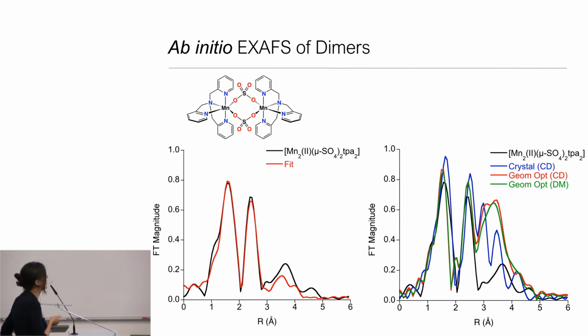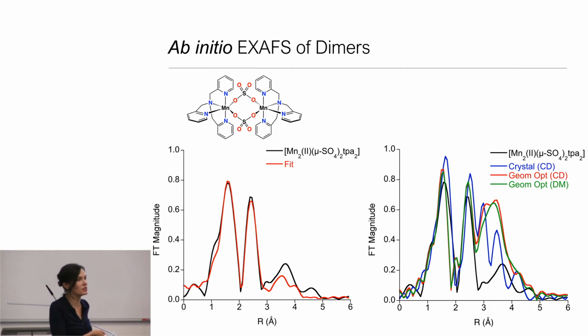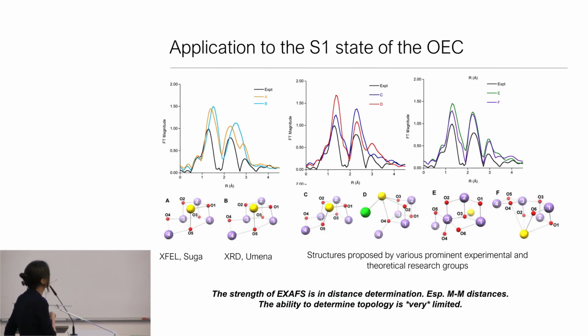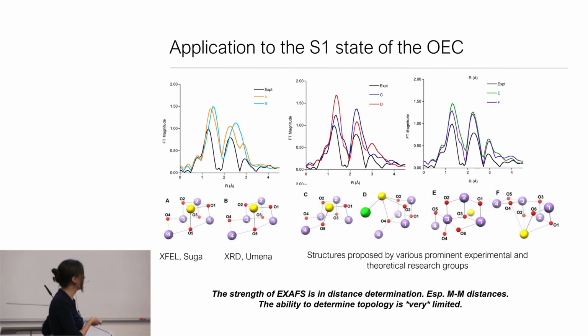But as soon as we get to more complex systems like dimers, again, I can fit it, but then all of my FEFF calculations, none of them match at longer range. And here I just want to point out that it remains the case that these scattering-based methods are still not fully predictive. They can't actually predict the damping at long distances. And so we used this some time ago to show that in systems like the oxygen evolving complex of photosystem II, you can't take a crystal structure and directly predict the EXAFS. That is still not possible.